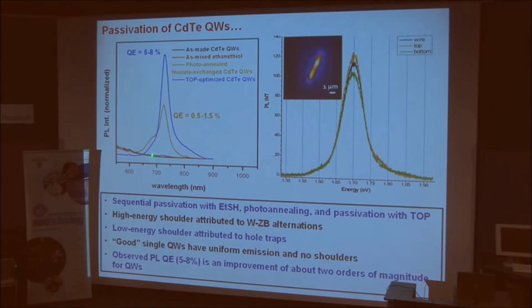And then if we first passivate sequentially with ethanethiol, we start to see a little photoluminescence. If we photoanneal, that is, just expose the wires to strong light, a feature starts to emerge. And then if we treat later with trioctylphosphine, we can optimize these bulk or ensemble quantum efficiencies to 5 to 8%, which is getting to be respectable.